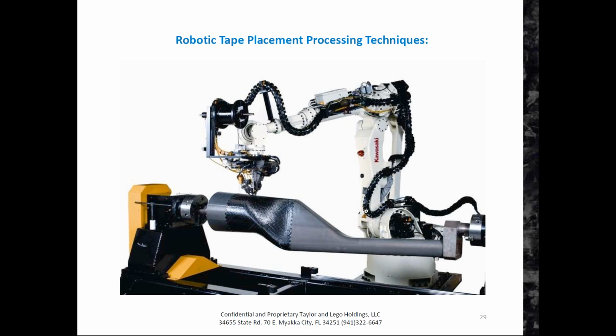But basically, these systems can also do thermoplastics. Right now it's applying a thermoset, but you could do thermoplastics, and some of these machines can be equipped with ultrasonic units that ultrasonically fuse the tape layers together in thermoplastic form, like PEEK or PPS, polyphenylene sulfide. Sometimes they will also use radiant heat or UV heat for fusing one layer to the other. So it's a pretty sophisticated process, but not fast. Of all the high-tech processes out there, this is probably one of the slowest.